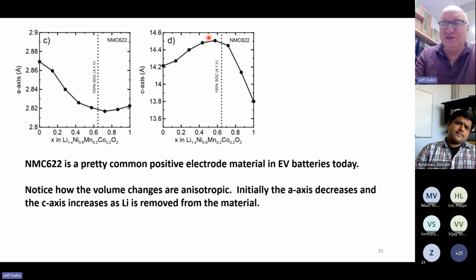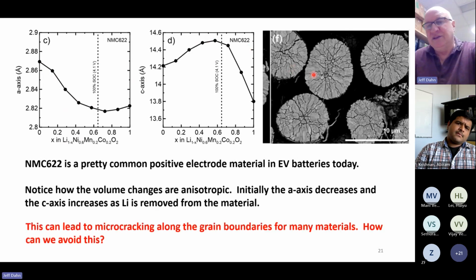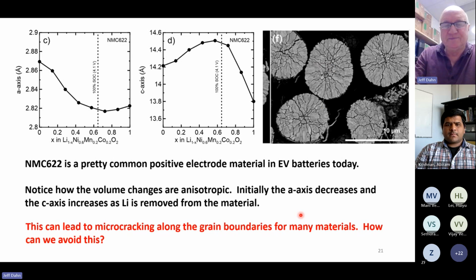And the problem with this is that you can get microcracking along the grain boundaries of these NMC particles, because one of them is expanding in one direction, the other in the other, and they're contacting each other, and it just shears along the grain boundary, and you get this microcracking. So how do we avoid microcracking?